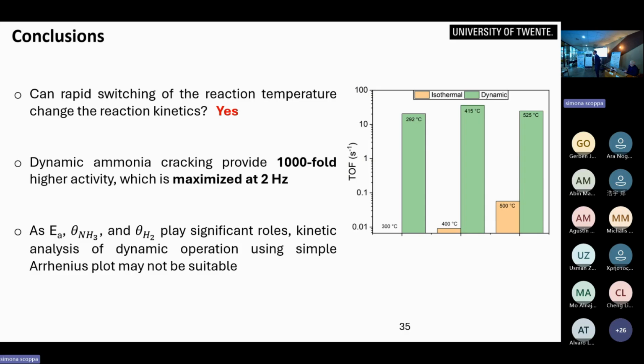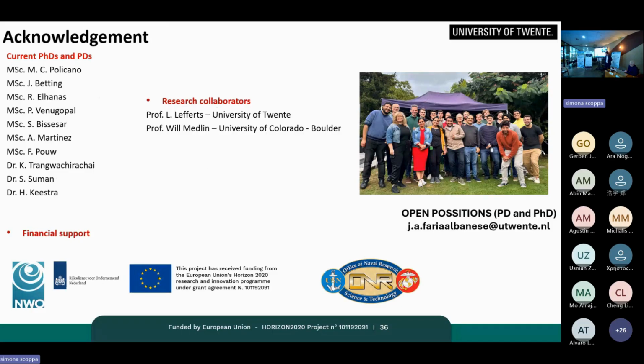In conclusion from this second part, the message that I want you to take home is that we can achieve very high reaction rates with this rapid switching. There seems to be a 1,000-fold increase in activity when we are at this sweet spot of 2 Hertz. We still don't know exactly why that is. We think that it has to do with the surface coverage. We're doing more calculations to prove that. So that's the conclusion. This is something that we're really looking forward to seeing how much further we can take.